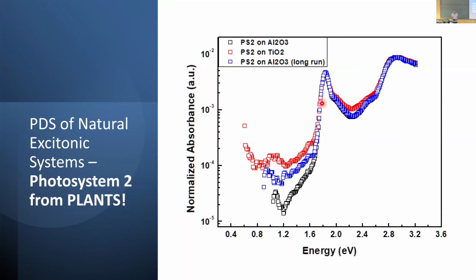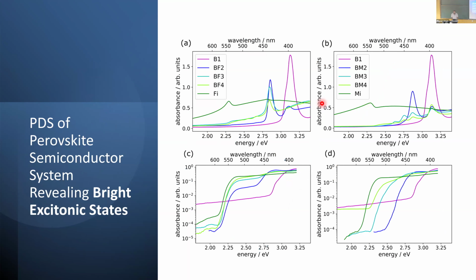Now if I go to other systems, perovskites, these systems also show a huge excitonic absorption. But there is one peculiar thing, and this is something we are looking at right now in our group. If you see this purple sample, this is an absorption curve in a normal absorption spectrometer. You can see a very huge absorption curve here, related to an excitonic absorption, which happens because the binding energies are very high. This happens to be a 2D perovskite with very high binding energies.